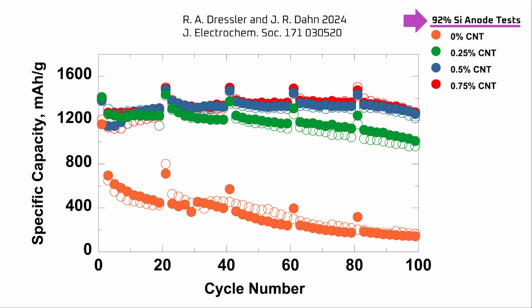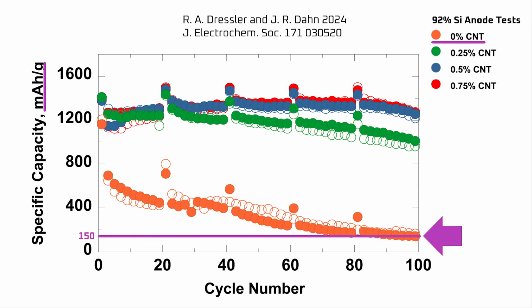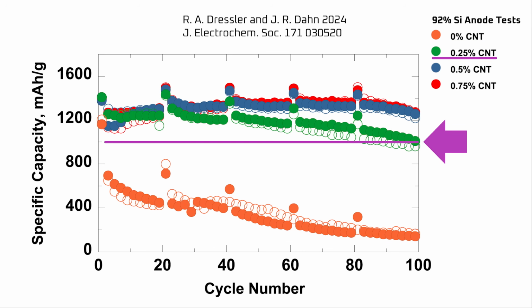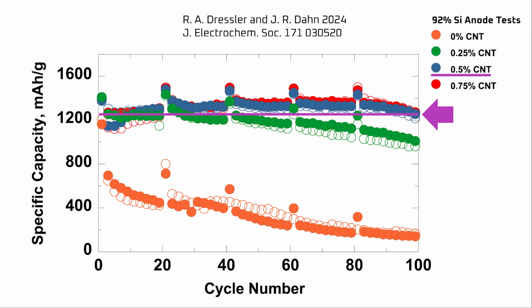Why does that matter? As this image from the Dahn research paper shows, for a 92% silicon anode with no carbon nanotubes, after 100 cycles, the test cells have about 150 mAh per gram of capacity remaining. With 0.25% single-wall carbon nanotubes by mass, there's about 1,000 mAh per gram of capacity remaining after 100 cycles. And at 0.5% by mass, degradation remains relatively flat and is minimized after 100 cycles, with 1,300 mAh per gram of capacity remaining. Adding more nanotubes to 0.75% had minimal further beneficial impact.